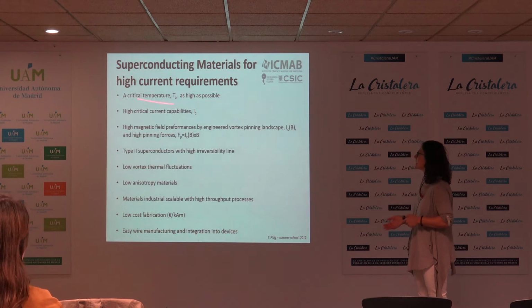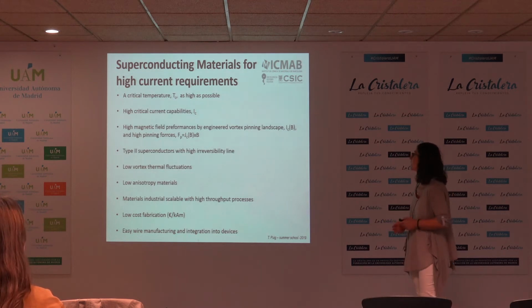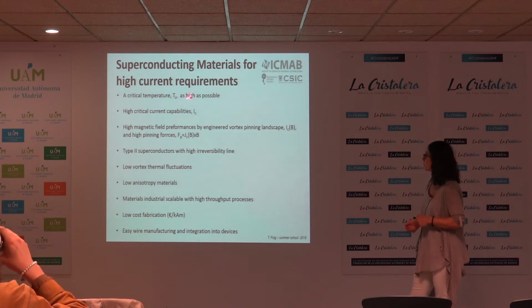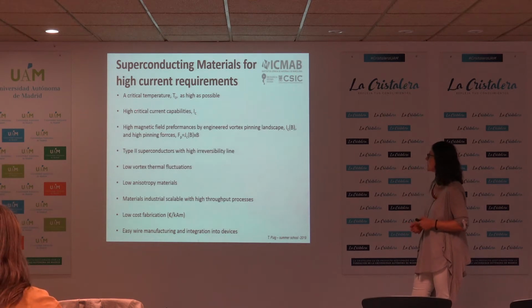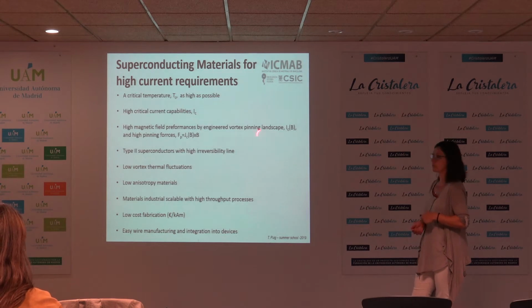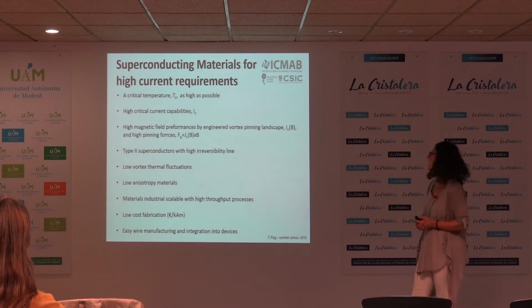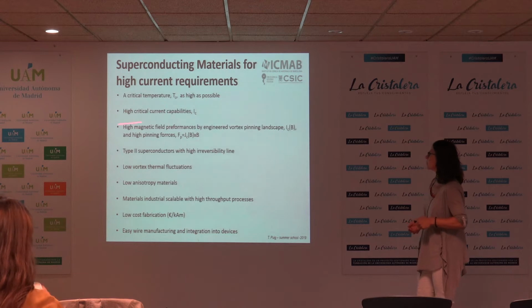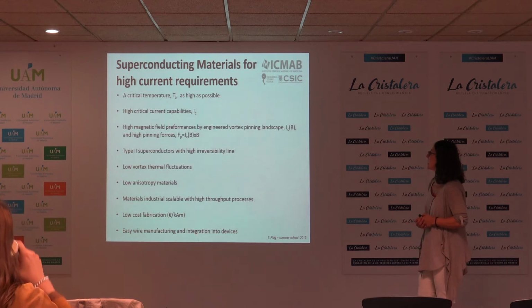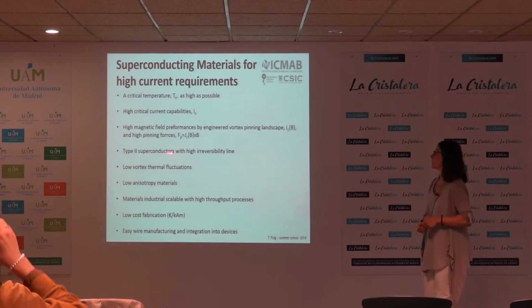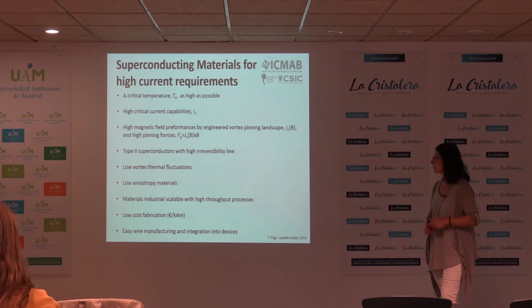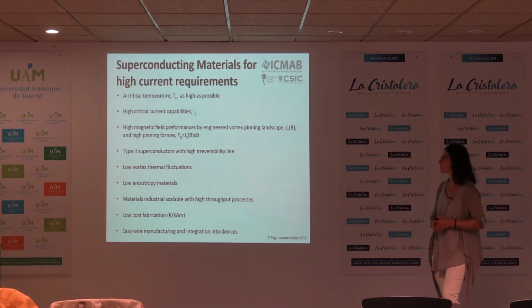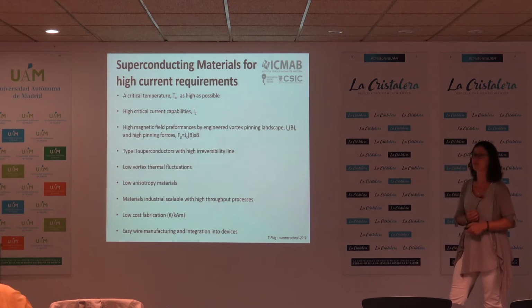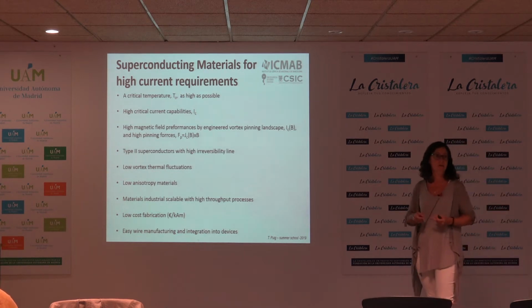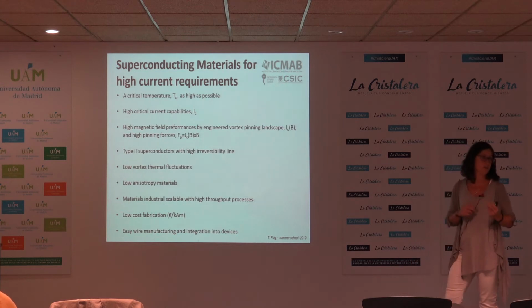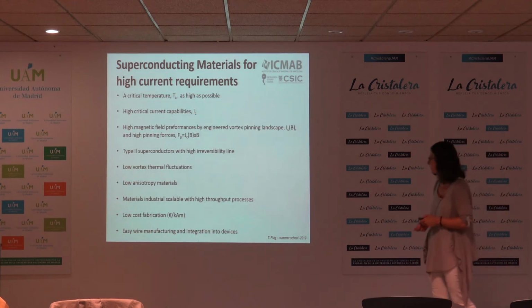So we need a critical current, of course, as high as possible. We need a critical temperature, a critical current as high as possible. A critical current as a function of magnetic field, okay, that is as high as possible, and that means that we need also high pinning forces. We need a type 2 superconductor with high irreversibility line. We need low thermal fluctuations. We need low anisotropic materials so that we are able to wind them without having to think about which direction the magnetic field is being applied to the material.